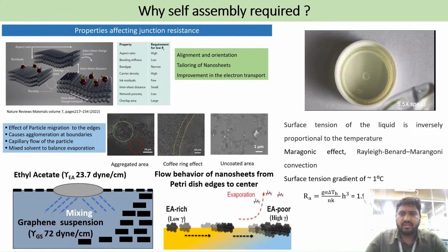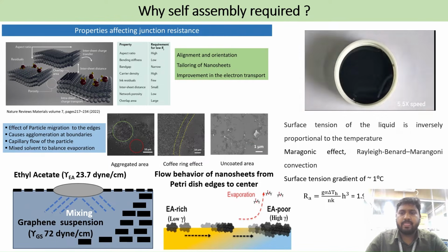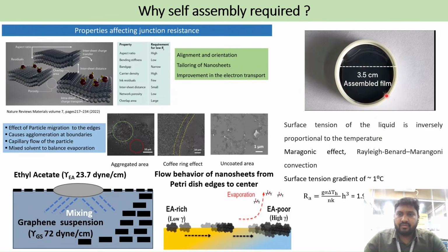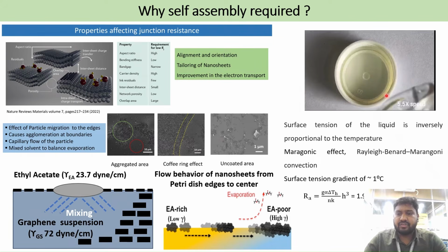Here we can see the video of interfacial self-assembly. The graphene suspension we added has a surface tension of 72 dynes per centimeter, and we added ethyl acetate, which is 23.7 dynes per centimeter. Due to the surface tension variation by the Marangoni effect, we can see the formation at the interface of a freestanding interfacial self-assembled film of 3.5 centimeters. And we achieved up to the 10 centimeter scale using different sizes of petri dishes, to transfer this into any arbitrary substrates.